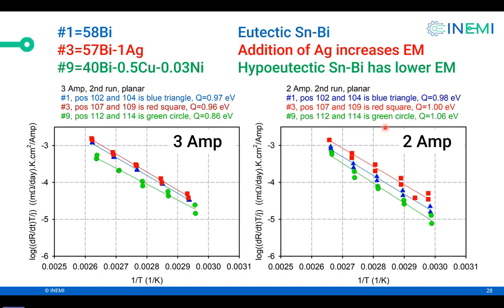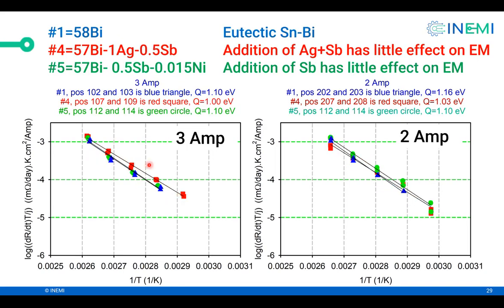I'll show you 4 charts quickly. Solder 1 is eutectic tin bismuth, solder 3 is eutectic with 1% silver, solder 9 is hypoeutectic. You see right away that the hypoeutectic has a lower electromigration rate, and the eutectic with a silver addition has a higher electromigration rate, and the blue one is just the eutectic. So addition of silver increases electromigration. The hypoeutectic solder joint has lower electromigration. So we go to the next test run.